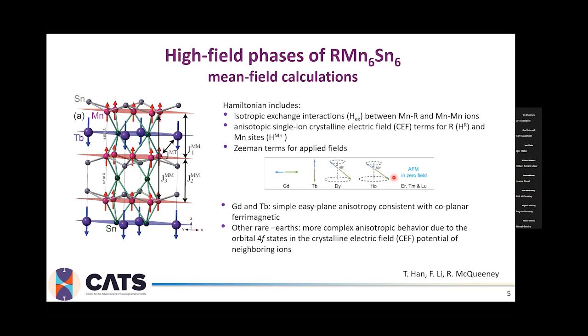The theoretical calculations were mean field calculations, which we got from Rob, and I believe he included in his Hamiltonian many different parameters, such as the exchange interaction between the manganese and rare earth and manganese ions. He also checked the influence of the crystalline electric field parameters, as well as the Zeeman terms for the applied magnetic field. Now, as I mentioned earlier, since there is a variety of different ground states, for example for gadolinium and terbium, those calculations seem relatively simple for predicting the magnetic phase diagram, but it becomes much more complicated in cases like erbium, when all the interactions become much more anisotropic, and we also have to check all the crystalline electric field parameters.